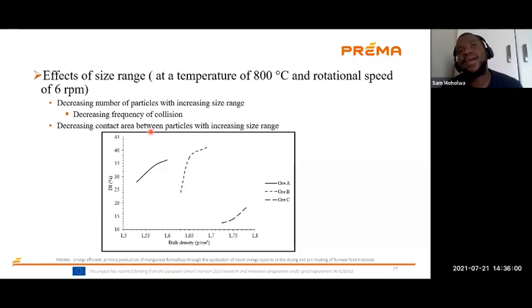Then the other one: when you have bulky big particles, the area of contact between individual particles is smaller, and bigger when you have a smaller number of particles. In other words, if you have a higher number of particles, these particles have a bigger area of contact between them, which will then produce fines due to the first 2 mechanisms, which were abrasion and attrition. This is why the DI decreases as the number of particles decreases, because the area of contact reduces and there's less friction between particles. Then less fines will be produced due to attrition and abrasion.